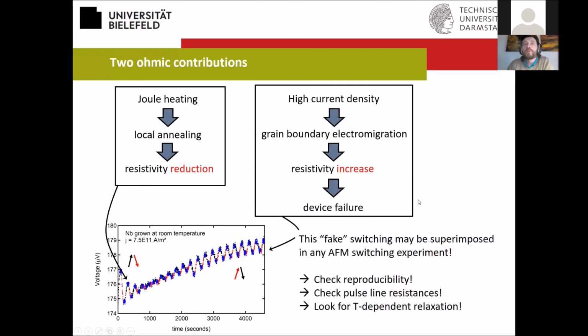So to summarize, this fake switching may be superimposed basically in any AFM switching experiment. What one should always do in these experiments is check the reproducibility, check the pulse line resistances and look at possible changes there, and look for temperature-dependent relaxation, because when you see this temperature-dependent relaxation, it's very probable that you actually look at something that originates from the magnetic system.